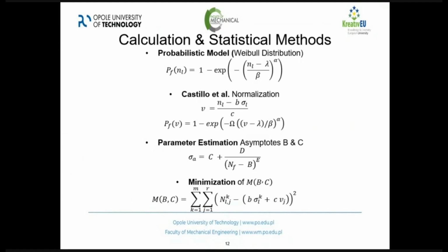And about the model and about the mathematics behind it. So we use the Weibull distribution, which I think fits well to the topic we are dealing with. Fatigue life is basically a probabilistic model with a bit of scatter, right? And the weakest link approach is, I think, quite well suited for 3D printed specimens. So this is why we use the Weibull model, but we also use the Castillo et al.